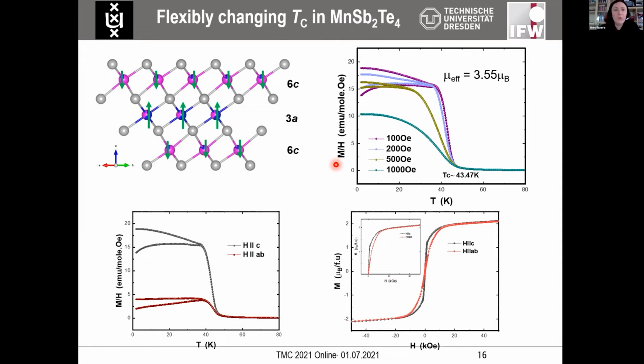It is not yet clear whether the coupling between these two sides within the septuple layer is antiferromagnetic or ferromagnetic. The saturated magnetic moment is still quite low compared to what would be expected for the full manganese 2+ configuration. And interestingly, if we get our samples in a slightly different way, the overall magnetic scheme looks the same, but the temperature keeps on shifting towards lower values.